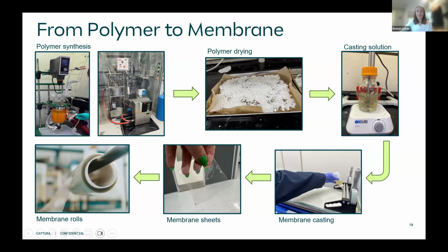We then take that powder, and one of the really key aspects in casting your own membrane is developing your casting solution. A lot of work has gone into developing what's actually in this little bottle. Obviously, we develop it at a much larger scale than what's just in that bottle there. But the solvents and ratios used in this casting solution are really critical when it comes to how the end product of the membrane turns out, especially for a multi-layered membrane like the bipolar membrane. We then use this casting solution to do initially in-house casting. The image here uses a doctor blade on a casting table: you simply put down your casting solution and the blade moves across the surface and casts a sheet of membrane.